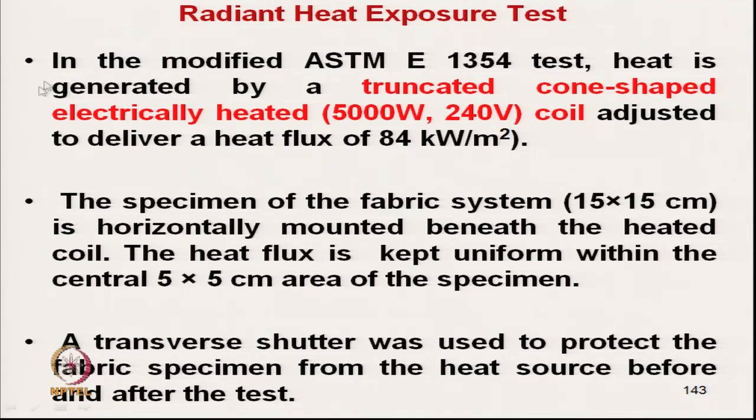And the heater is 5 kilowatt, 240 volt. Okay. The specimen of the fabric system, that is 15 by 15 centimeter, is placed horizontally, mounted beneath the heated coil.